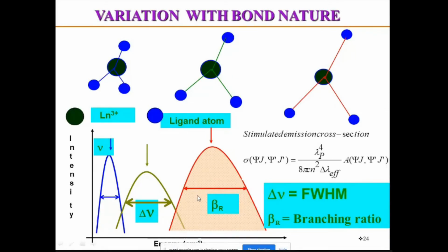So if you want to use this material for optical devices, for display devices, I can tune its emission position or absorption position, I can tune its width, and I can choose the area under the curve. So these are all the factors I am able to measure, and I am going to call them stimulated emission cross section, or absorption cross section, or width, and the area under the curve is called the branching ratio. So just by changing the environment, by changing the active ion, and by changing the modifier and the activator, I'm able to prepare a variety of glasses.